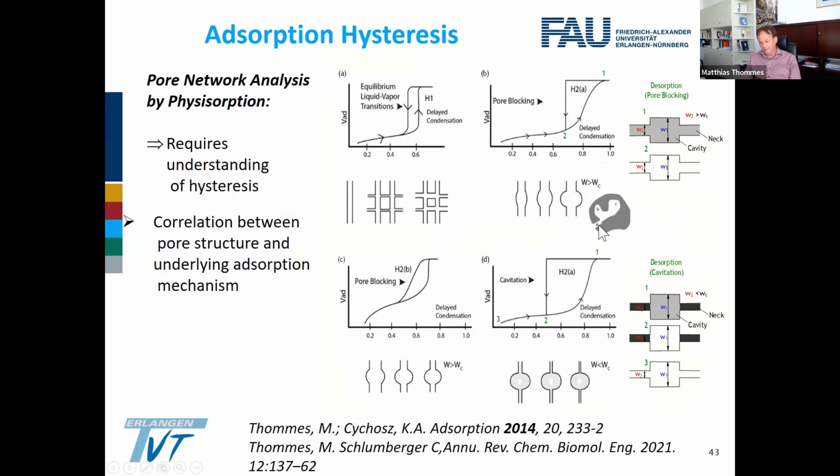And this is a more classical picture of a porous system where you have a narrow neck and all the liquid, which essentially adsorbs as a function of pore size. So the adsorption branch is correlated with the size distribution, but the desorption is essentially very steep because the liquid which is trapped in the pores C and B can only leave if you reach a pressure which is associated with the size of the neck.